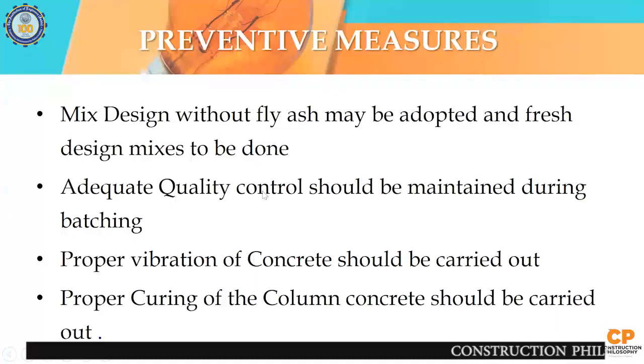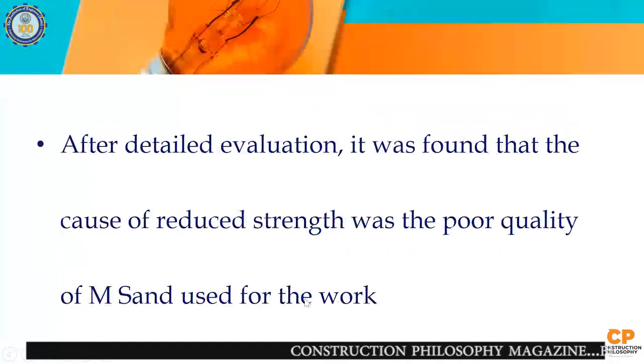The cement brand was changed. Quality control team experts: we brought in about 3 to 4 concrete experts to work out what the real problem was. Vibration of concrete was suspected, curing of the column was suspected, and finally, after detailed evaluation and study, we found that the M sand which was used had lesser aggregate and the quality was poor, and that had led to all this sort of problem.